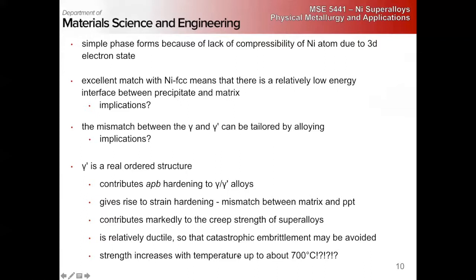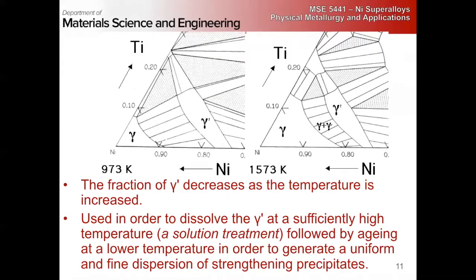And then also there's something odd about this. The strength increases with temperature up to about 700 C. We'll talk a lot about this. This is called anomalous strengthening of superalloys, right? Most materials, of course, get softer as you raise the temperature, right? But in superalloys, we get an increase in strength. Something makes the gamma prime more difficult to cut as you increase the temperature, which seems very counterintuitive because you increase the temperature, you have more thermal energy available for dislocation motion. What it does is it actually opens up other channels of motion that lead to making the dislocations more sessile, right? So you have more sessile dislocations as you go up in temperature. It's a weird thing, and we'll talk about it in more detail.